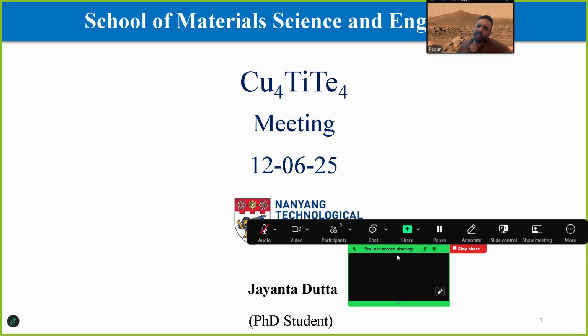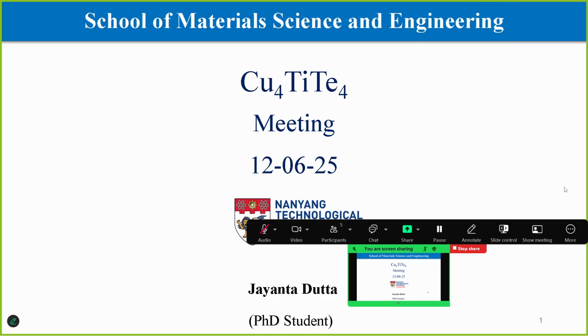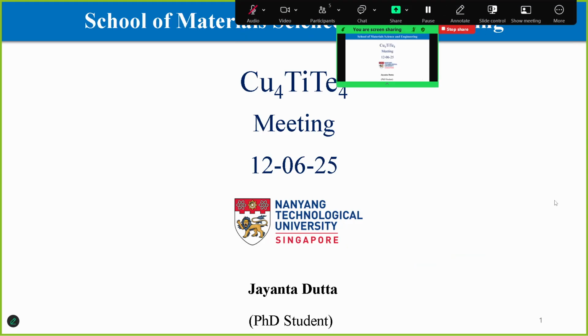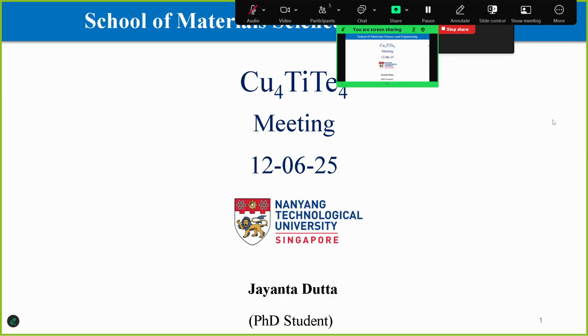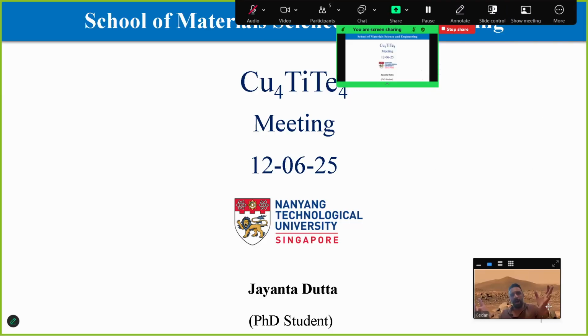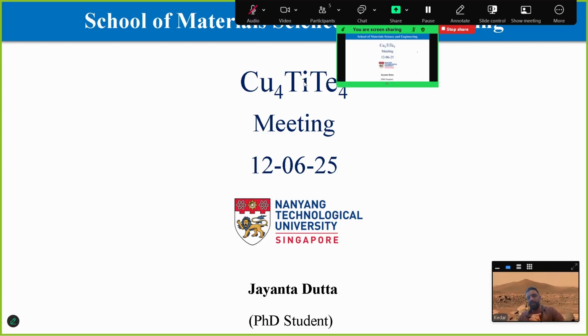Even induction heating has been around for the longest time. If you think about the principle of this rapid Joule heating, the Joule heat is going through the powder, okay? This is a heuristic opinion, right? The atoms, especially copper and stuff, have high ionic migration. So when you put current Joule heat through it, they will migrate under a field, which gives you good mixing and allows you to somehow form these beautiful phases.